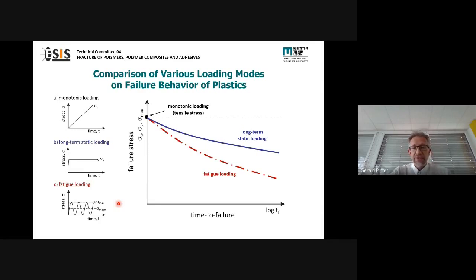However, if we use fatigue loads, we even see a much stronger decrease in the failure stress over time, so over cycle numbers, because in addition, we also have damage that is developing in the material, and this leads to a further decrease of the failure stress. Therefore, fatigue is so important to handle, and if design engineers do not cover this aspect, that the maximum stress that the component can survive is decreasing over cycle number, this can be the reason that sometimes components fail quite surprisingly.